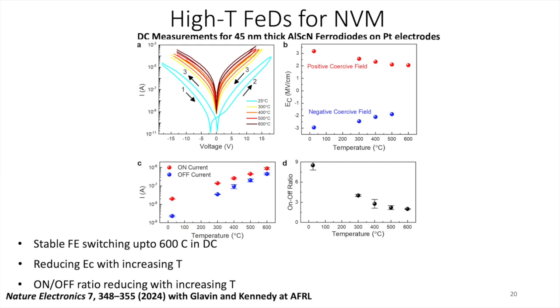Or 3 essentially. And that means that once you have crossed path 1 to 2, you have changed the state from a high resistance state to low resistance state. And so this hysteresis is basically a signature of memory, that if you follow path 1 to 2, you'll stay on one state. If you follow path 3, you are on the other state. And so this kind of hysteresis is maintained quite well. You can see the hysteresis all the way up to the brown curve, which is 600 degrees Celsius curve.